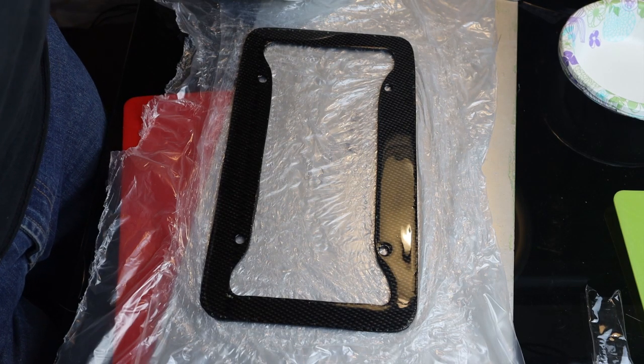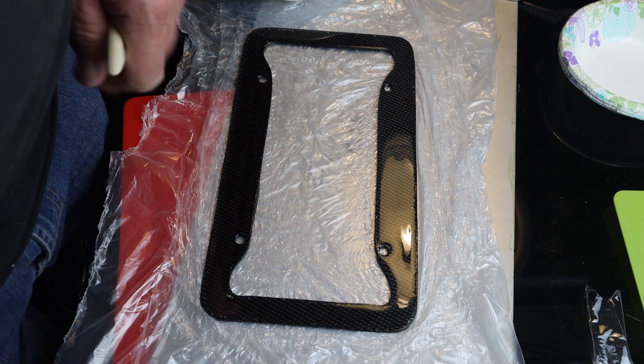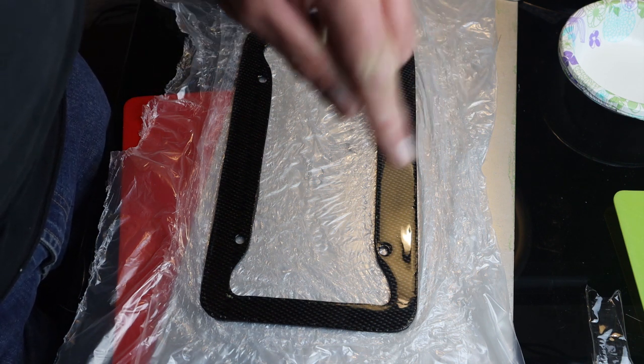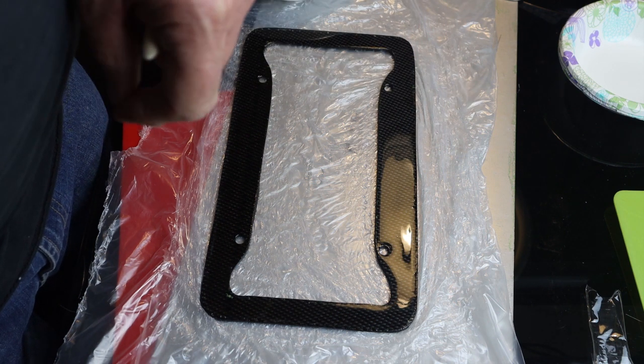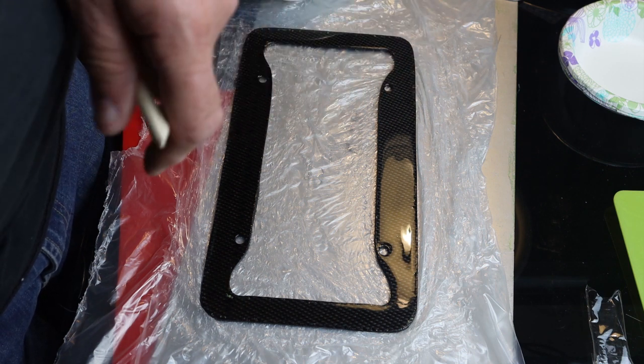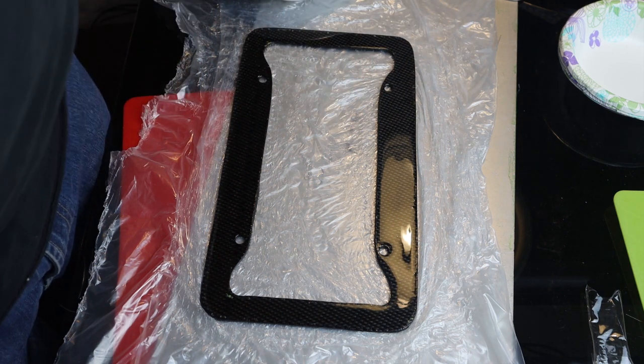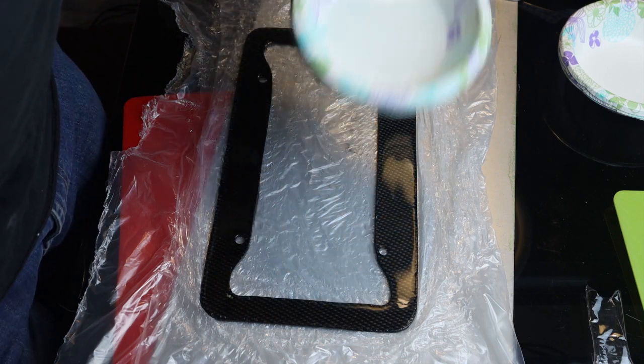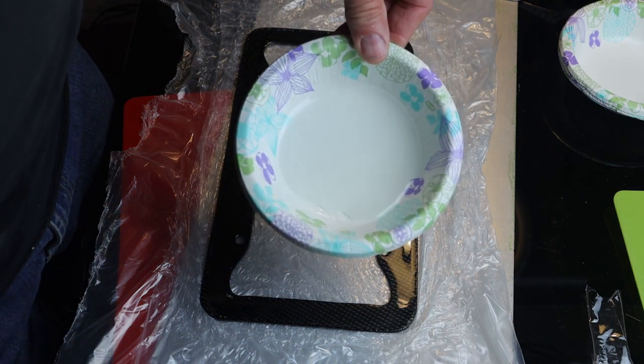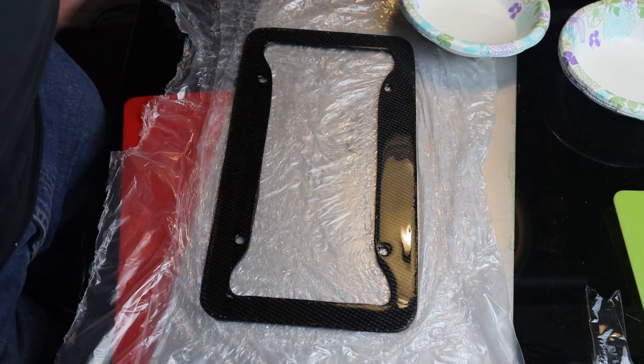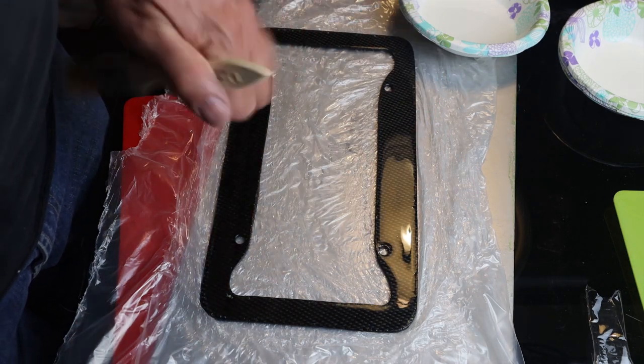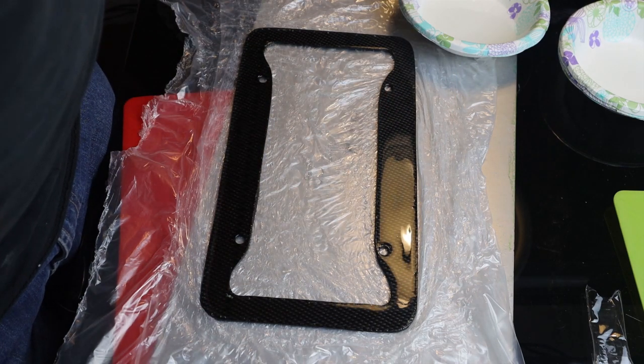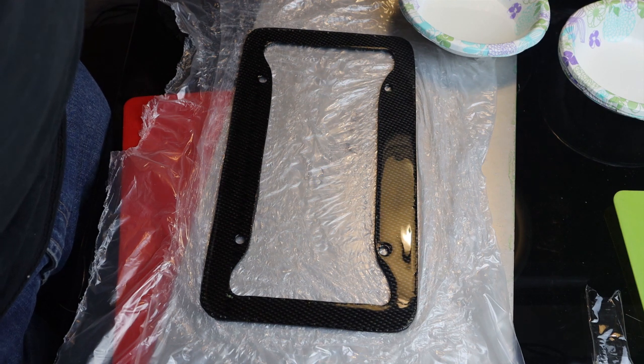It's been just over 5 hours. The resin is just slightly tacky to touch, doesn't leave an imprint on your finger. So we're ready to do the second coat. We've mixed up another 20 grams of resin. And the nice thing is the second coat should fill in any imperfections that were left in the first coat.